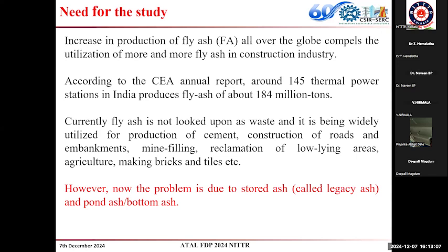So if we are able to reduce the cement consumption in concrete, then we are contributing towards the circular economy for net zero emission. When we are using fly ash in cement, we are getting a dual advantage. One is that cement consumption is getting reduced. That depends upon what amount of fly ash we are using. The Indian code suggests that we can go up to 35% of replacement.